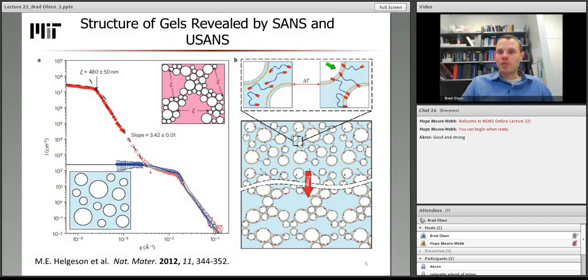As you raise the temperature of the material, the end groups on the polyethylene glycol, which are somewhat hydrophobic, will tend to insert into this surfactant layer on the outside of the oil droplet, and therefore become anchored in the edges of the droplets. Because each polymer chain has 2 ends, it can anchor into 2 separate droplets, and this provides a short-range attraction, basically due to this physical cross-linking between droplets. So you essentially introduce an effective attractive interaction due to the bridging of these chains, and that effective attractive interaction leads to not a coalescence, excuse me, but a sort of aggregation of the droplets into a network structure, which is illustrated down here on the bottom side of the picture.